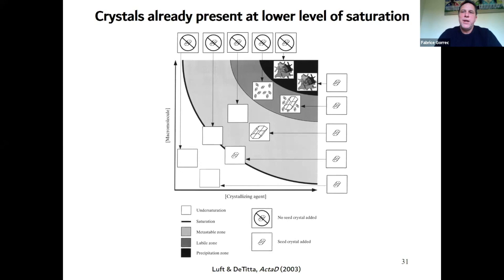The crystals you use are either microcrystals, and there are different techniques for seeding. So you can grab microcrystals simply by stroking the drops where they are, and then place them the same way in the other drops. You can also fish larger crystals that you have, fragment them by crushing them, and then introduce them in the new experiments. So the screen you're going to use for this is going to be optimized accordingly to the saturation level. Or you could simply rescreen with initial screens, with a random aspect again with the seeds.